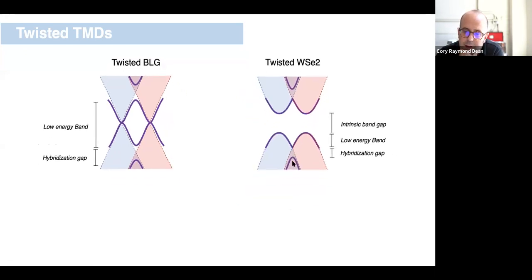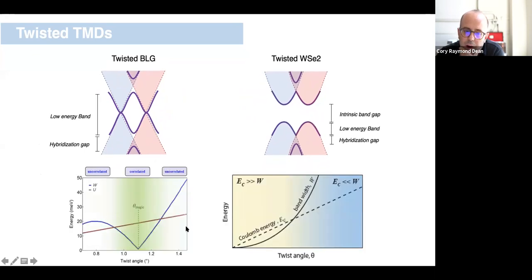So what that means in some schematic way is that while for twisted bilayer graphene there's a precisely defined magic angle at which you have the minimally flat band, in twisted homobilayer TMDs you imagine that the width of this band grows continuously as you twist the two layers. Now, the relevant feature here is not just how flat the band is, that's an important parameter, but that it's related to what the Coulomb energy is in the system. We're interested in stabilizing correlated, interaction energy driven states. And the way one hopes to do that is not just that the band is minimally flat, but that the bandwidth is less than the Coulomb energy. So really it's that ratio between the two that's defined at a well-defined magic angle in twisted bilayer graphene.